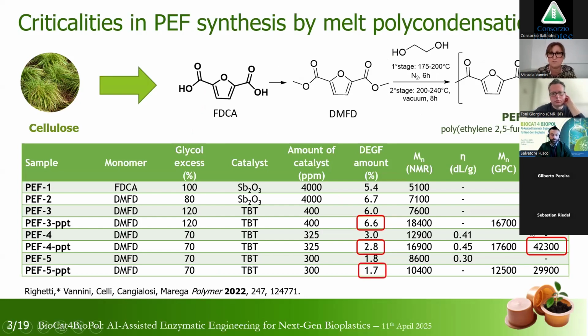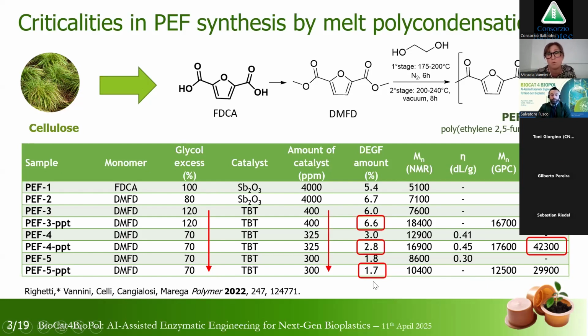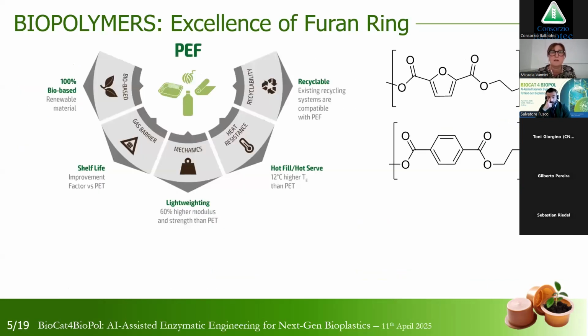We tried to prepare PEF with low content of DEG, and you can see that a reduction in the catalyst amount - the titanium-based catalyst - and also a reduction in the glycol excess resulted in a PEF with the appropriate molecular weight but also with low DEG content.